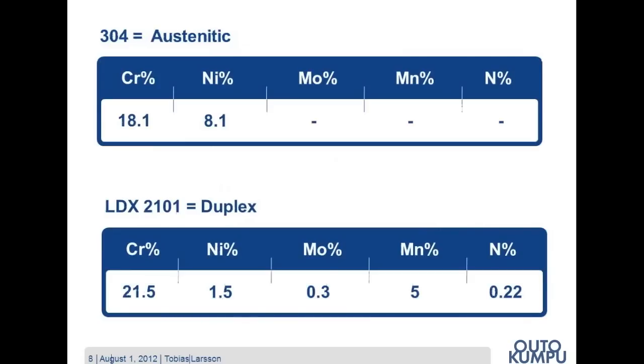Taking a look at the chemical composition of the austenitic grade 304 compared with the lean duplex grade LDX2101, you can see that we have substituted the expensive nickel with molybdenum, manganese, and nitrogen, which all are cheap in comparison with nickel except for the molybdenum, but this is in small amounts. So it has a good corrosion resistance thanks to the high chromium content, and it's been further optimized with the other alloys.